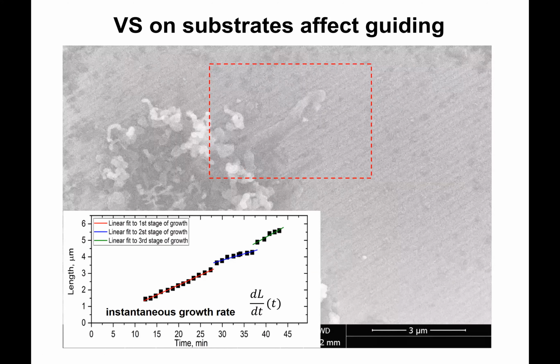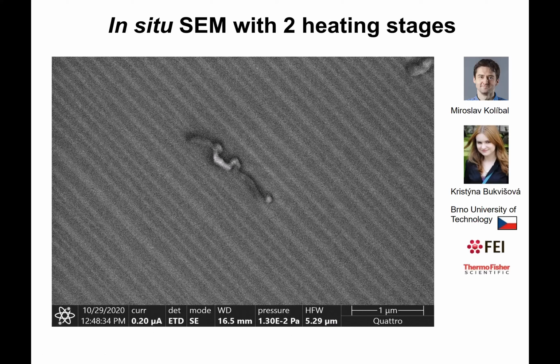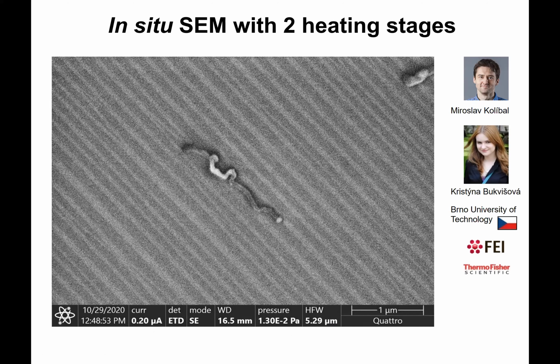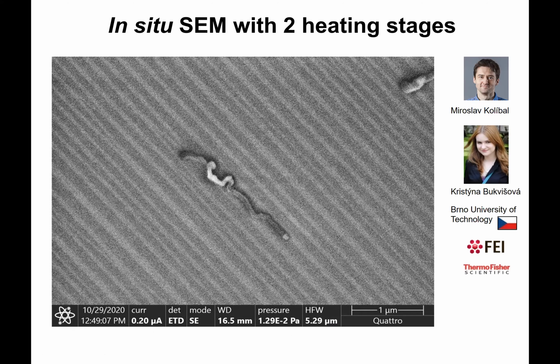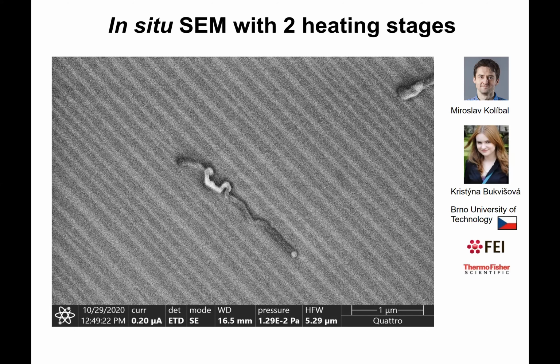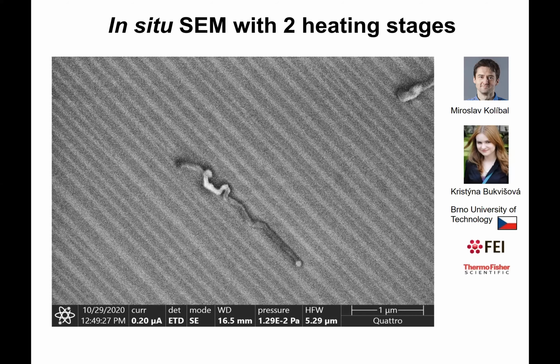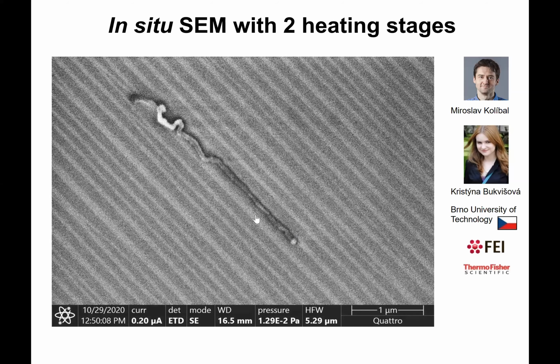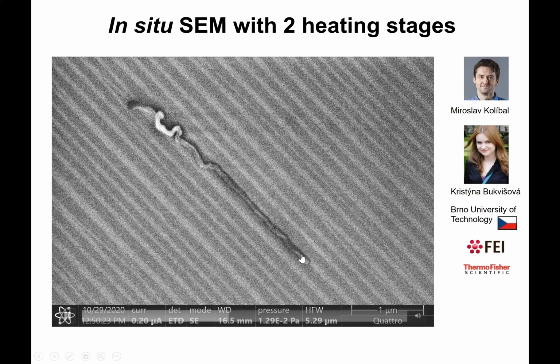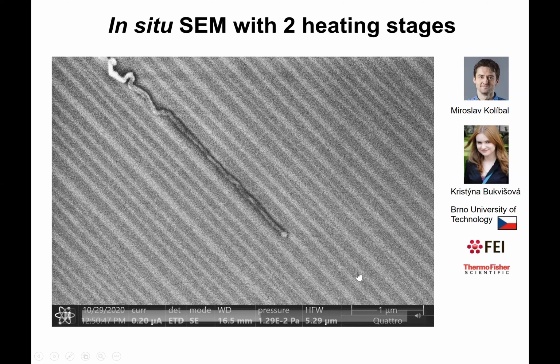This is an experiment done at FEI, which produces the SEM and the heating stages, with our collaborators in the Czech Republic, who followed precisely our recipe but with 2 heating stages instead of 1, giving them more control. You can see how the nanowires are growing along the step.